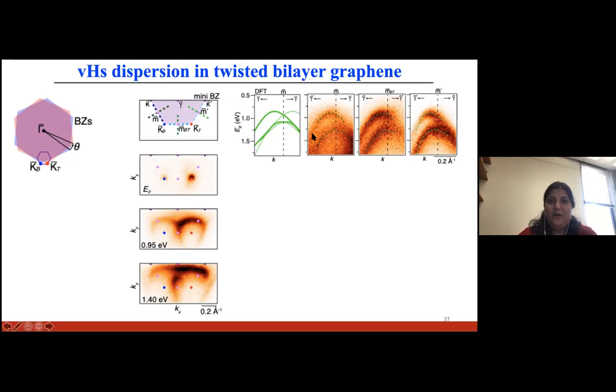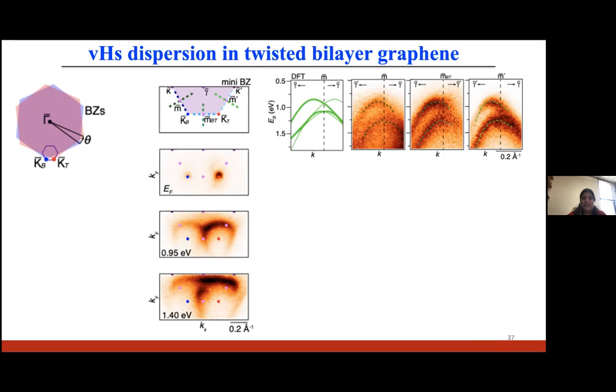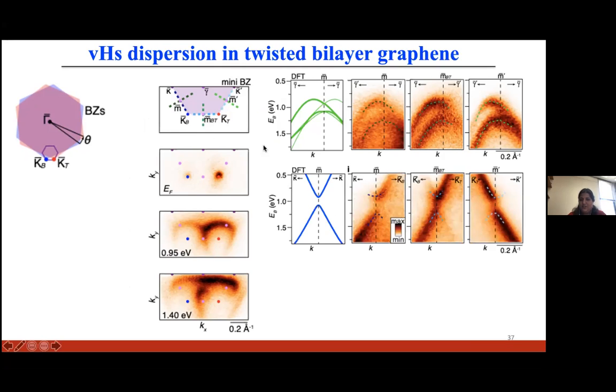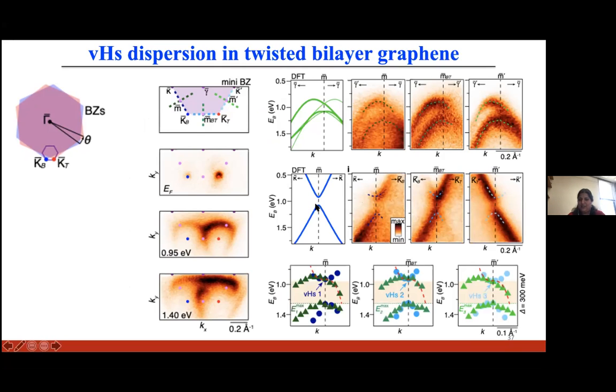And similarly, we can now look at the dispersion along this direction, which is K_B, M_BT, K_T, and similarly along this direction and this direction, which I am showing here. And here what we observe is that there are upward curving bands. And again, these bands match with the DFT calculations.